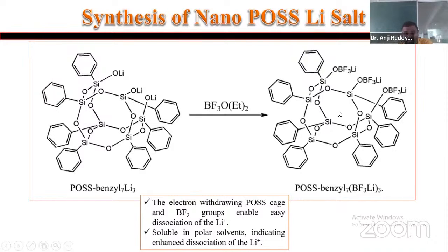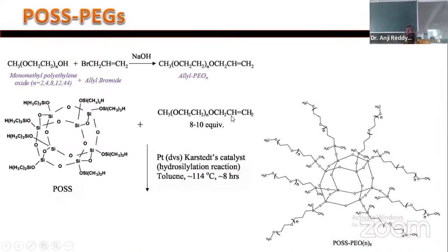This lithium salt we synthesize, and we also synthesize some POSS-based polymers, for example POSS-PEGs. We can use these POSS-PEGs as a polymer or a plasticizer. This is the first step of the POSS-PEG synthesis. This monomethyl polyethylene oxide is available in the market, and it is reacted with allyl bromide. First, we synthesized allyl-terminated PEO with different chain lengths. Based on chain length, we can use it as a plasticizer or a polymer.